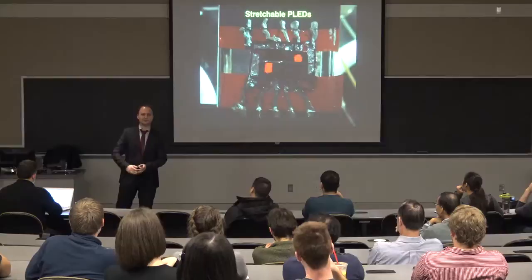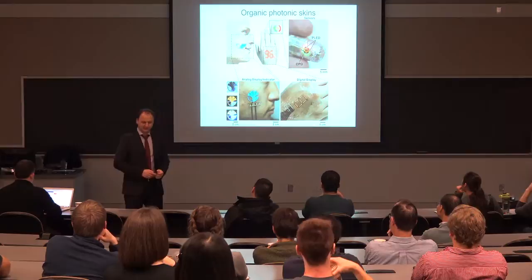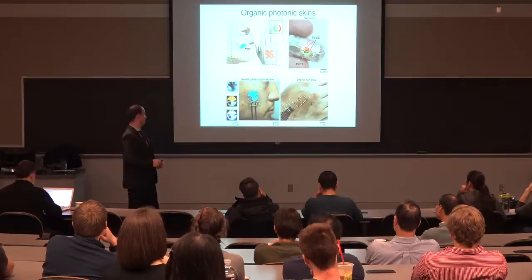This is our contribution to that field. The more advanced devices we did in collaboration with the guys in Tokyo. Of course, the examples that I showed you up to now weren't all that air stable. They had no barrier properties in terms of water and oxygen. You can, however, design 1 micron thick substrates by using alternate layers of, for example, silicon nitrides, oxides, and polymers. Those would be a sufficiently large water and oxygen permeation barrier.